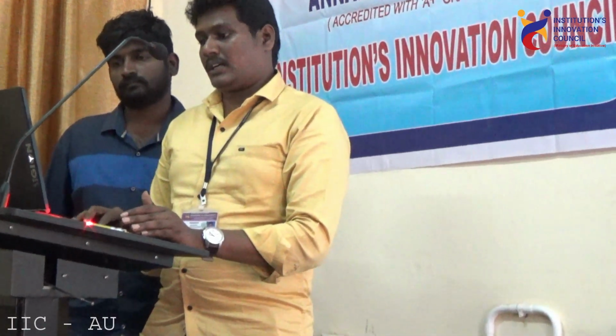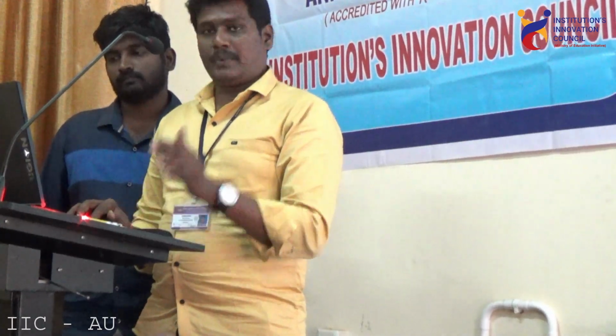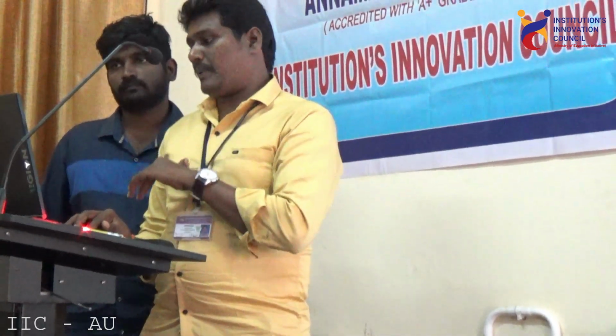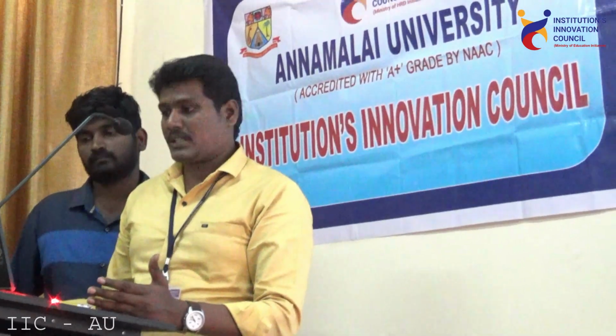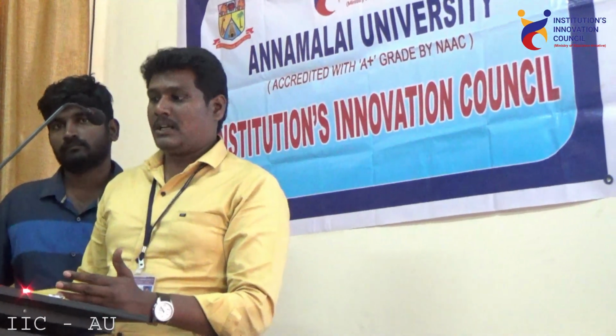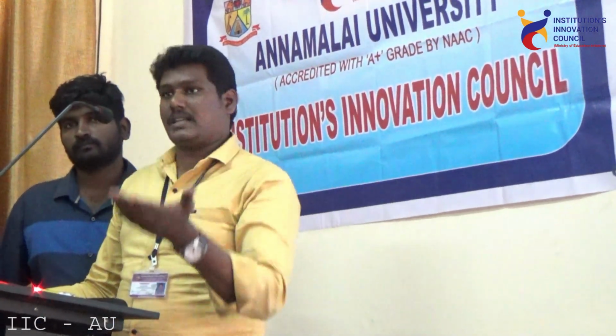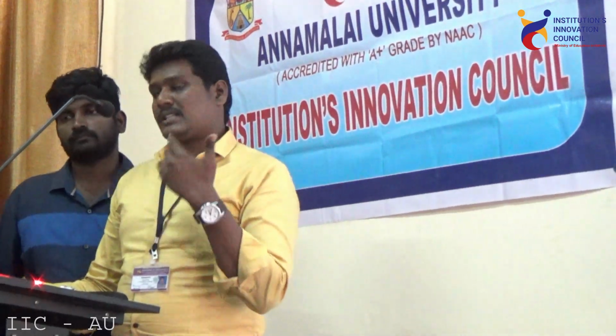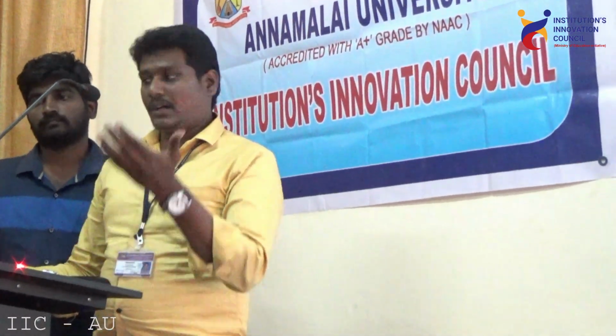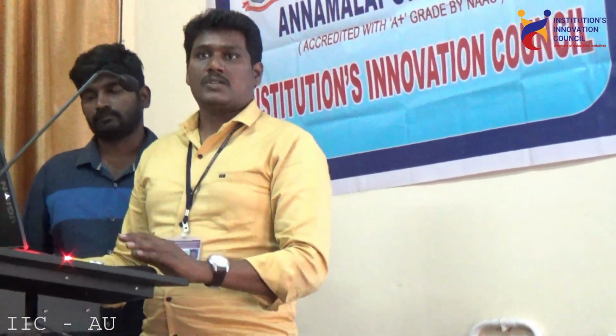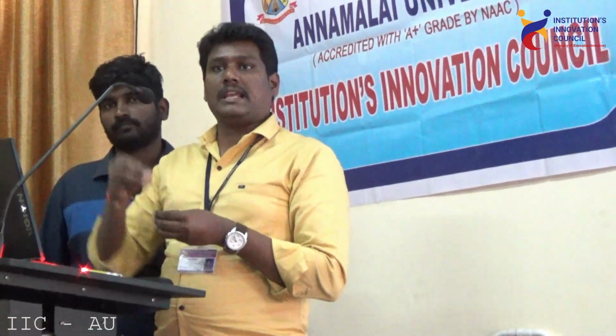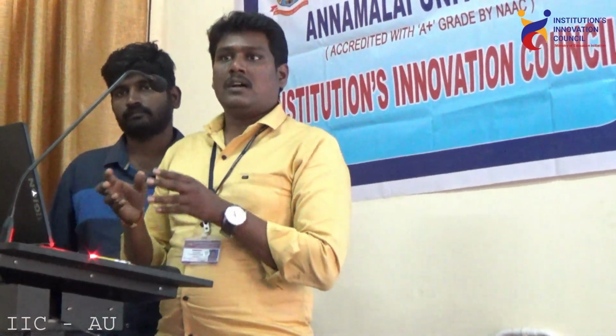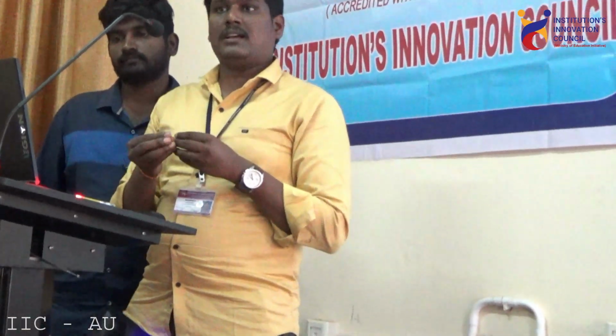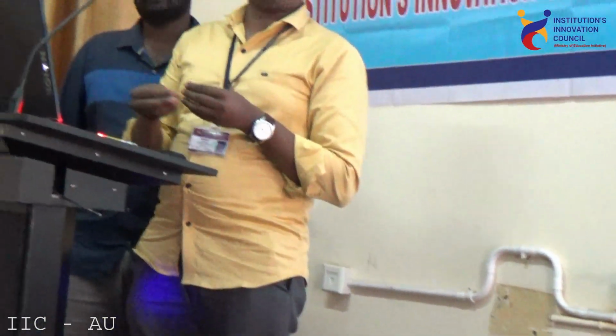In both components, the top region produces a lesser number of pores when compared to the bottom region. When compared between the processes, the CMT components produce fewer pores and smaller pore diameter and pore area. So this is technically the reason for the increased strength of the CMT component. And we also went for SEM analysis for both the CMT and GMAW processes.